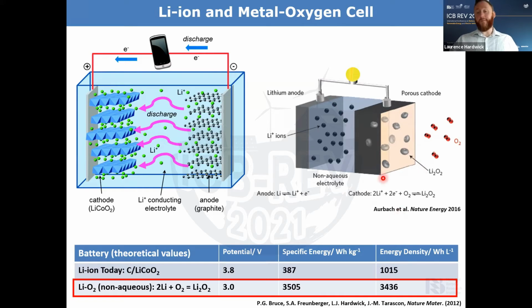And then what's been found is that this reaction has some reversibility, and this is part of the challenge of lithium-air batteries, to get this much more reversible and understand how to control some of these side reactions. So you have an operational cell where on discharge you're forming the lithium peroxide, and when you're charging it, you're oxidizing back to oxygen. So you have an open cell where oxygen is moving in and out of the electrode. The motivation for this is a very simple back of the envelope calculation, which shows that you can get much greater theoretical specific energies when you're doing this type of chemistry rather than the intercalation chemistry.